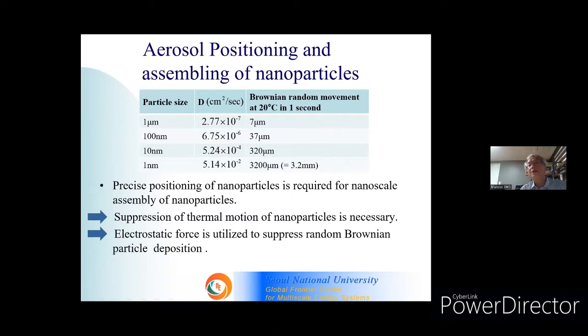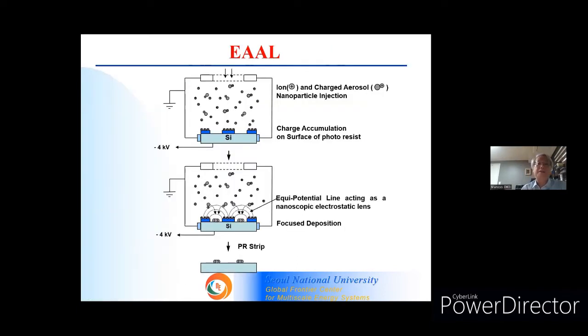But in order to make a 3-dimensional nanostructure, you have to manipulate your nanoparticles within nanometer scale resolution. That means we have to suppress this Brownian motion. So in our method, we use electrostatic force to suppress random Brownian particle deposition.